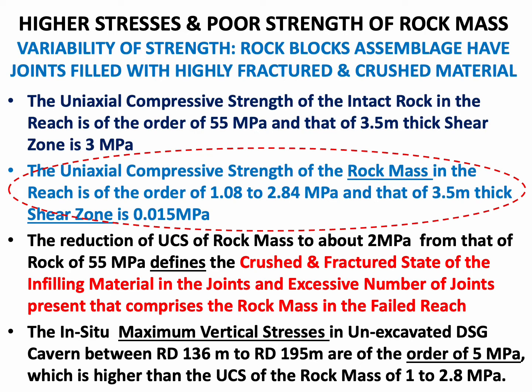The uniaxial compressive strength of the intact rock in the reach was of the order of 55 MPa, and that of the 3.5 meter thick shear zone was 3 MPa. This is the uniaxial compressive strength of intact rock, not the rock mass. The uniaxial compressive strength of the intact rock was 55 MPa, and that of the shear zone was 3 MPa. The uniaxial compressive strength of the rock mass, in comparison to the rock, in the reach is of the order of only 1.08 to 2.84 MPa, and the rock mass strength of the shear zone was only 0.015 MPa.